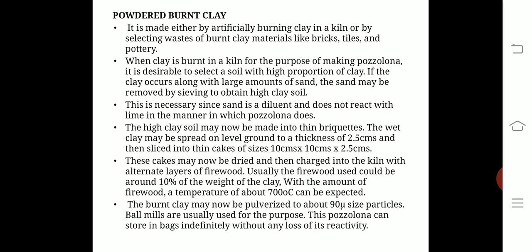Let us start with powdered burnt clay. It is made either by artificially burning clay in a kiln or by selecting wastes of burnt clay materials like bricks, tiles, and pottery. When clay is burnt in a kiln for making pozzolano, it is desirable to select a soil with a high proportion of clay. If the clay occurs along with a large amount of sand, the sand may be removed by sieving to obtain high clay soil. This is necessary since sand does not react with lime the way pozzolano does.